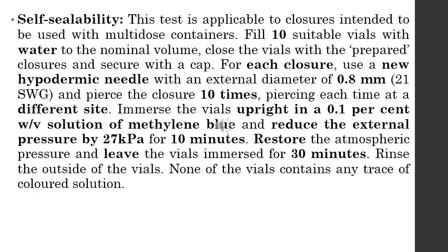Next test is self-sealability test. Now this is again applicable for closures which are intended to be used with multi-dose container. In this case, 10 vials are selected which are filled with water. Now these are securely closed, and then with the help of hypodermic needle whose external diameter is about 0.8 mm, we have to pierce the closure for 10 times at 10 different places.